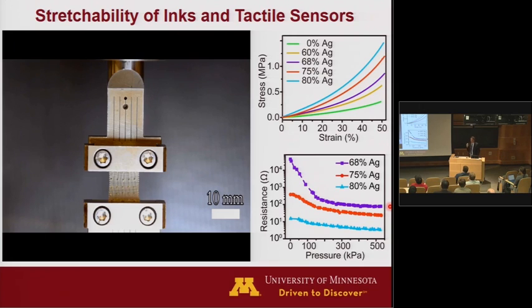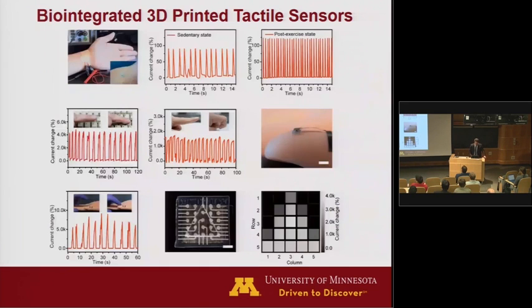And we can actually get gauge factors of these devices up to about 180, which is almost on par with a single crystal semiconductor. So you can see here that this device is sensitive enough that you can merge it onto your wrist, as you can see here. And my student was able to measure his pulse in a sedentary state. Then he went running around the block and came back, and you can see that the amplitude and frequency increases with the increased pulse frequency here.